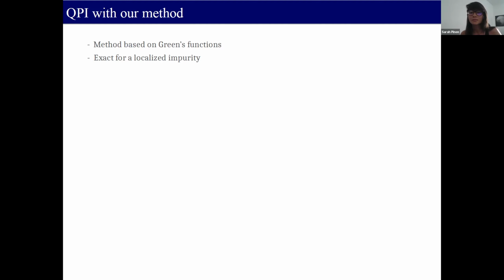No. I mean, can it be that the exact Green's function could be cast in such a form that you have some sort of SSP-like form for the thing that you see? So can you cast it? Is there something else? So I would assume that the true local density of states, you build up your local density of states from the particles on the Fermi surface, and in principle, if you would know all the matrix elements, not just the spin part of the matrix elements, but the proper matrix elements between the states, you should recover a formula which looks like the formula for the SSP, but with an altered matrix element.